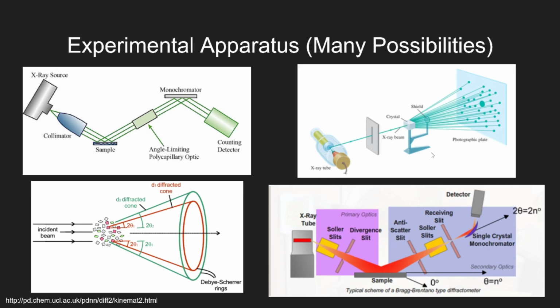There could be stress and strain factors that, if you have a powder that's been pressed down in a certain way, might accidentally give it a preferred orientation. And that depends a lot on how large the crystal flecks are. If they aren't small enough, then they might have some sort of preferred orientation that's inherent in them already. And that ties in with grain size.